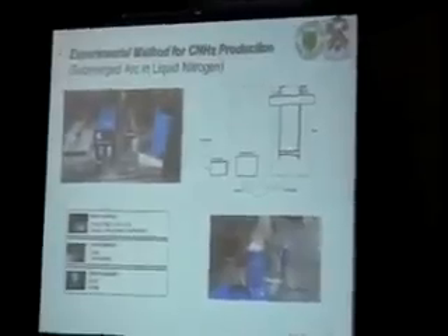Going to our experimental methods. This is the setup that has been built to generate carbon nanohorns. It consists of a Dewar flask, DC power supply, ammeter, voltmeter, and the control box. This schematic shows the discharge process. In order to generate the nanohorns, two graphite rods, anode and cathode rods of 99% purity, have to be submerged in liquid nitrogen contained in the Dewar flask. The 1 mm arc between the anode and the cathode is maintained by using the control box, which automatically adjusts the motor feed screw as the anode side gets sublimated or consumed.